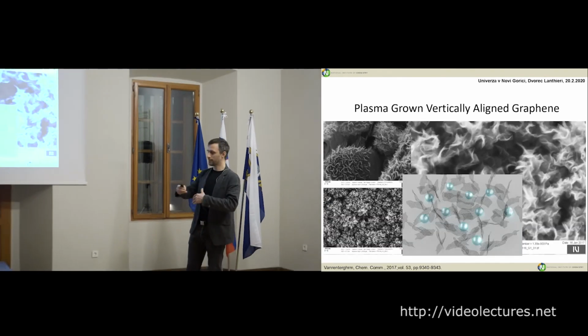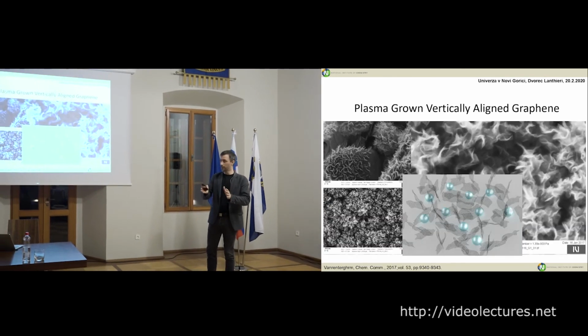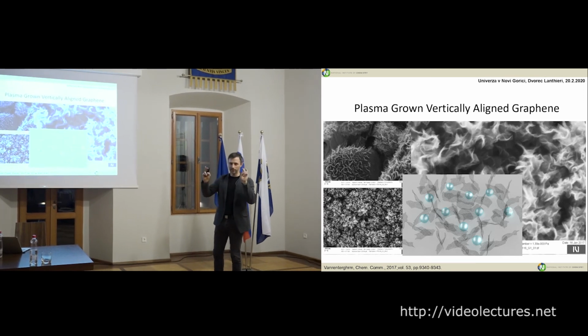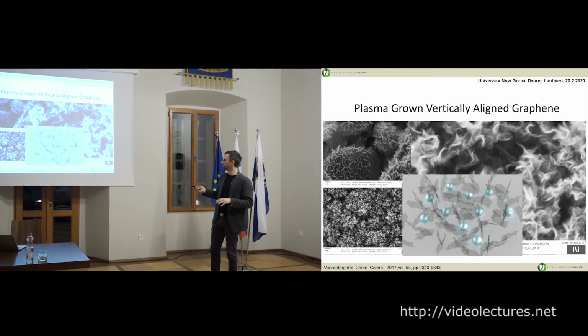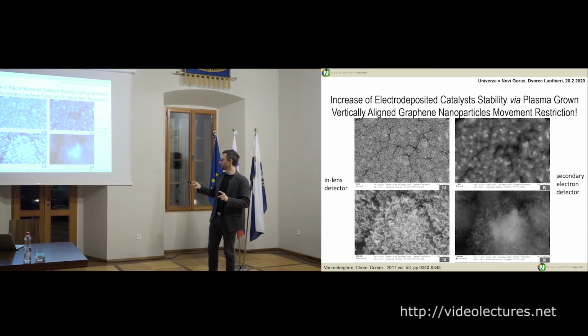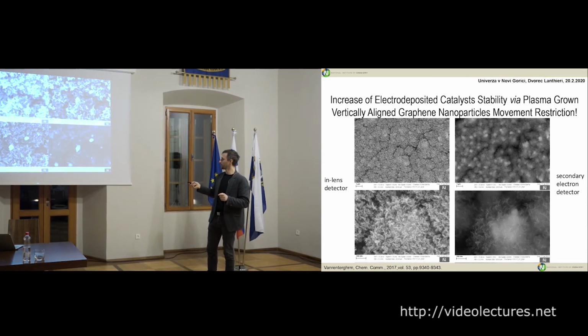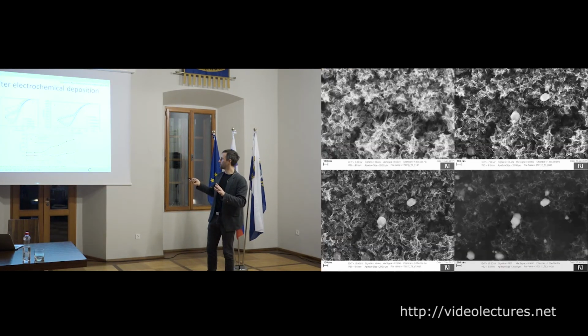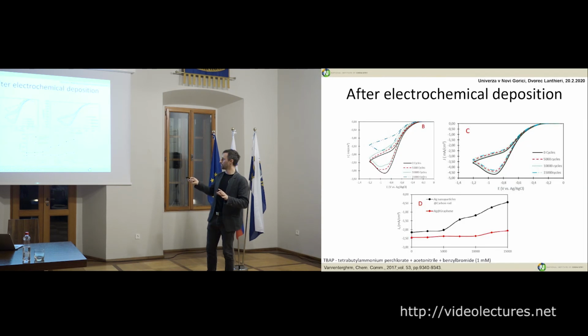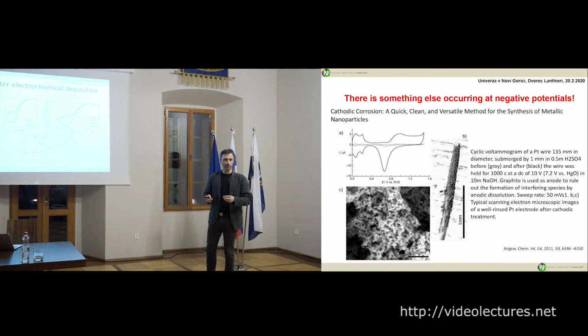Here we made vertical graphene fences, and then we prevent the movement. So we nicely embed particles. I will just skip, but we can see if we make this graphene, we actually prevent the loss of activity. This is without graphene and with graphene. So if you know the degradation mechanism, you can prevent it.